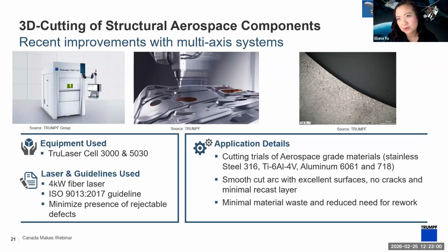What we found was not every material that we did the cuts on was 100% perfect, but on the whole, with the new parameters and trending towards looking for these kinds of defects on large smooth arcs, you can cut with excellent surface, excellent fast speed, no cracks, and a minimal recast layer. According to using this spec as a guideline, we got great results with a variety of different materials. What that means to the manufacturer is, if you're looking at this as a process, you're now going to be able to have good quality cuts overall with minimum material waste and reduced need for rework. All those things lend to driving costs down, being more productive, and also having a knock-on effect on your amount of inventory and rejectable products for defects. So these are all good news.